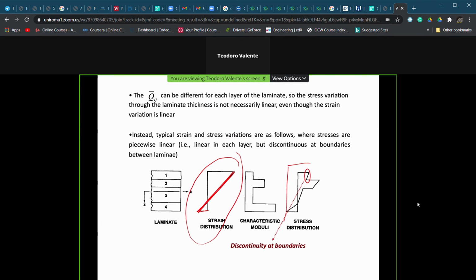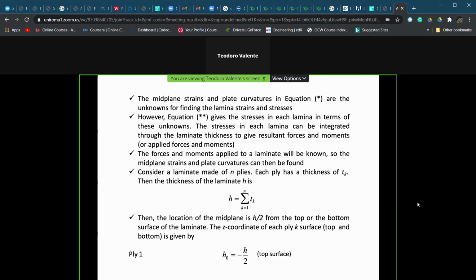But this with discontinuity in stress distribution. So strain continuous, but stress discontinuous, because if the lamina 1 has properties A11, and if the lamina 2 has properties A11 of the lamina 2, which are different, obviously, depending on the orientation, that's a general approach. Obviously, in this case, the values of the strain must be different.